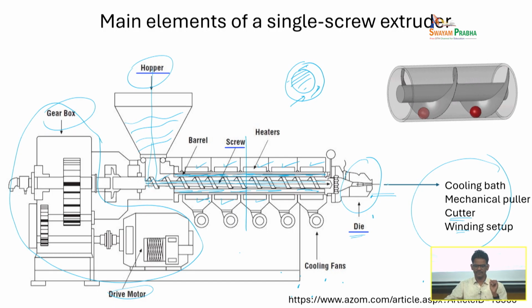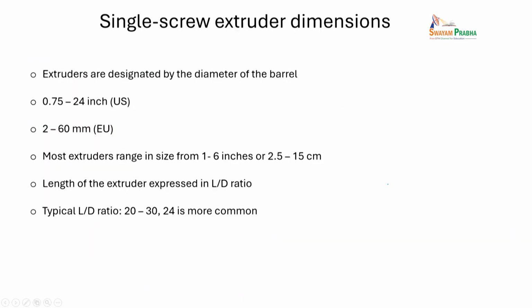So now an extruder can be designated or represented by the diameter of the barrel. Typically this diameter can be as small as 0.75 inch, or it can be as big as a 24-inch barrel diameter. And in the extruders that are typically manufactured in Europe, they go anything between 2 to 60 millimeter from the lowest to the highest. But in the industrial scale, typical diameter of the barrel can go anywhere from 1 to 6 inches, or in other words 2.5 to 15 centimeter.